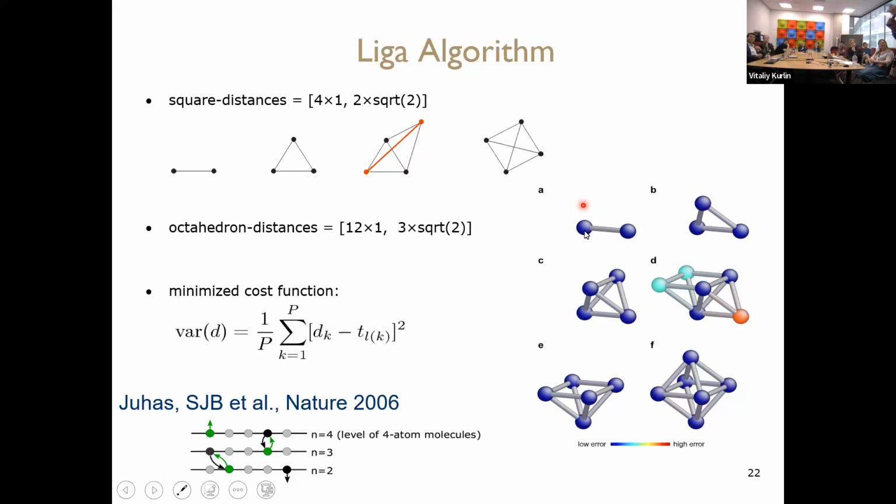So we'll pick 2 atoms on our cluster, and then 2 distances from our distance list, and we'll triangulate onto that. Now, our first 3D object is when we take a 4th atom out of our box and triangulate it onto our 2D structure. So we now have to pick 3 atoms on the cluster, 3 distances from the distance list, and we triangulate it on modulo 2, because it could be on the left or the right side.